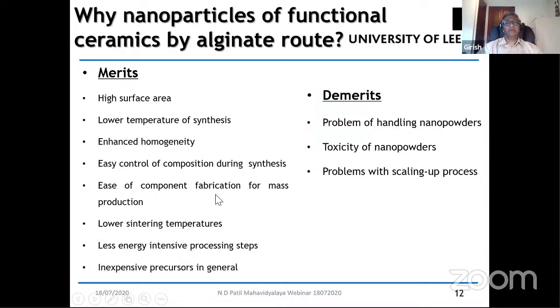It is relatively cheaper to produce components out of the powders on a mass scale. The sintering temperatures are lower because every material in a fuel cell needs to be sintered so that it is dense. And because of the nano size or high surface area of the powders that are produced, it is able to sinter at much lower temperatures compared to conventional powders. It is a less energy intensive process, and it uses inexpensive precursors. So the precursors are inexpensive. You don't need organometallic precursors. And also the alginate that is used is relatively inexpensive.